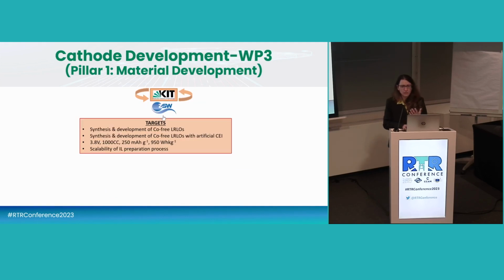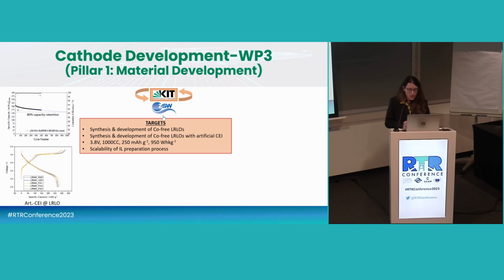Another important aspect of the cell chemistry was the cathode. This part is led from the KIT in Germany, and they were able to tackle the big problem of the cathode, that is how we can have a longer cycle life by keeping at least the 80% of the capacity retention. Here in this specific figure that I'm showing you, we achieve, with a very high specific capacity, the 80% of capacity retention for the first 500 cycles.